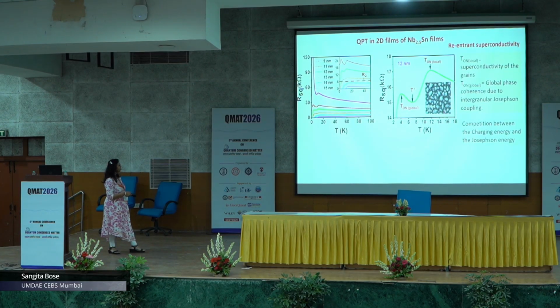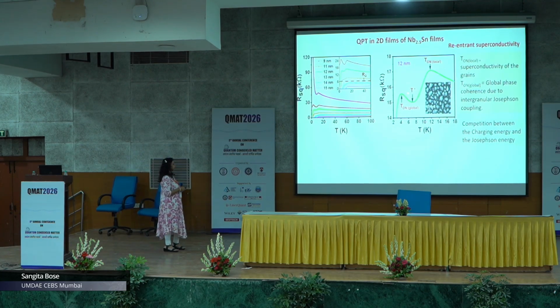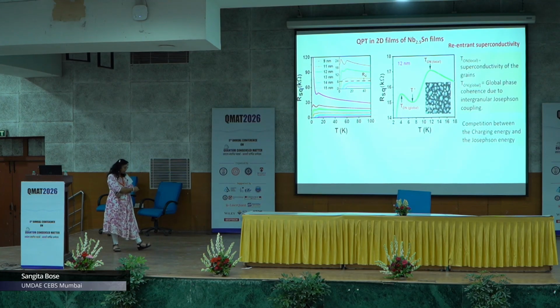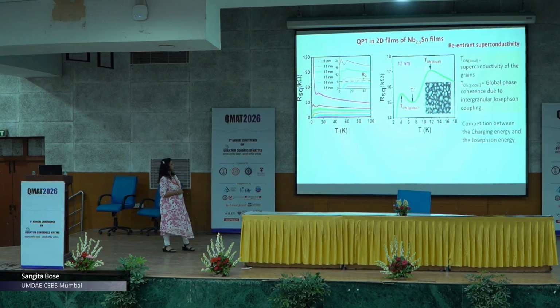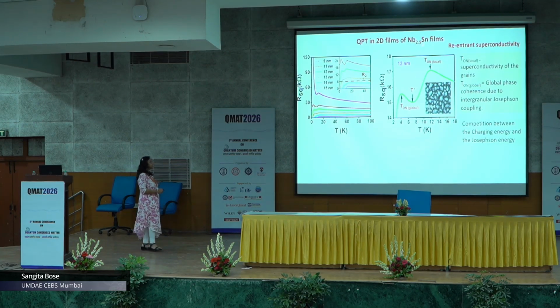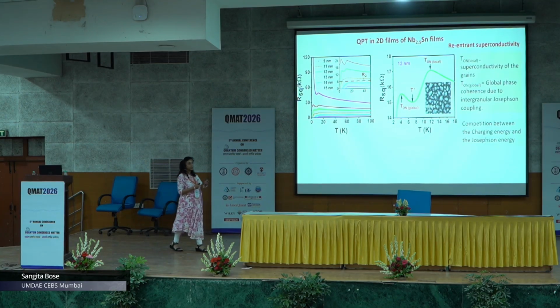You see this blown up over here for one of the films, the 12 nanometer film. This was the microstructure, very granular in nature, small grains separated by intergranular boundaries, and you see this, this and this. So basically you see two drops. How do we understand this reentrant behavior? What we first point out as the onset, where the resistance starts decreasing for the first time, we christen T onset local. We mean that our grains are just becoming superconducting at this temperature T onset.